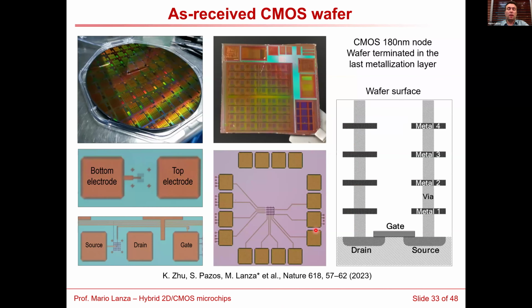So then we fabricated some CMOS wafers, 300 millimeter with 180 nanometer CMOS technology in a foundry. And then we terminated the wafers in the last metallization layer, okay? We did not passivate the wafers. Then we cut the wafers. We cut each microchip, as you can see here. And this microchip contains many test structures.